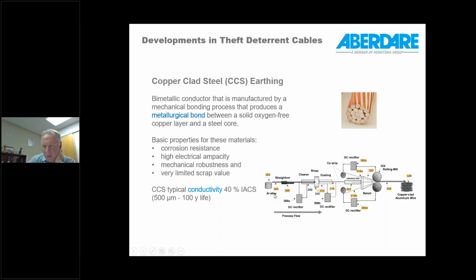This picture shows aluminium alloy, but the process is exactly the same also for steel. So the input here would be steel and the output would be copper-clad steel. Under high temperature and high pressure, these copper strips are applied onto a metallurgically clean steel substrate, and it's pressed together and then immediately drawn down to smaller sizes, so that there's a metallurgical bond between the two materials.